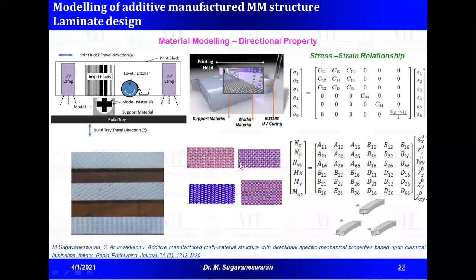We have also tried to place secondary material within the primary material based on different loading conditions. For this we took a reference from classical lamination theory, which is generally used for composite materials. If we look into the composite material, the positioning and layup sequence will help us understand the behavior of a material, whether it has bending resistance or twisting resistance, or whether it has superior strength at the outermost layer. This can be designed by using the CLT relation, the classical lamination theory relation.